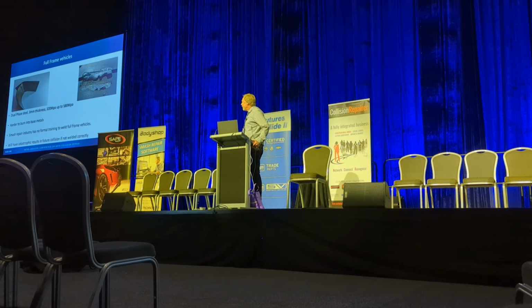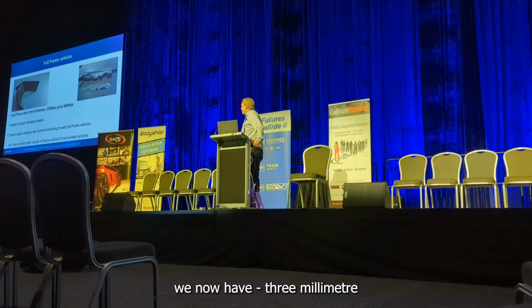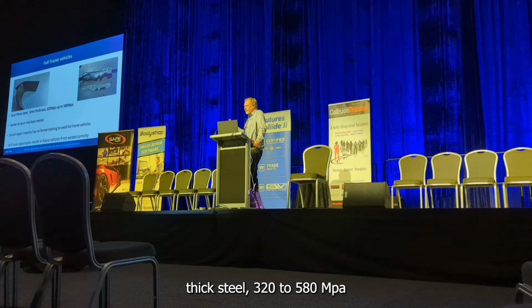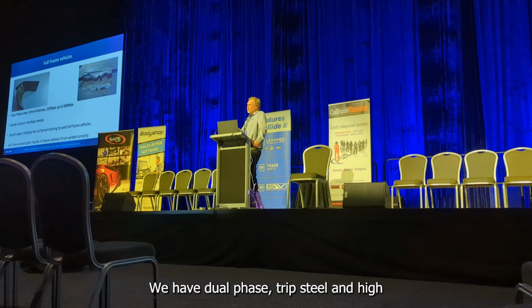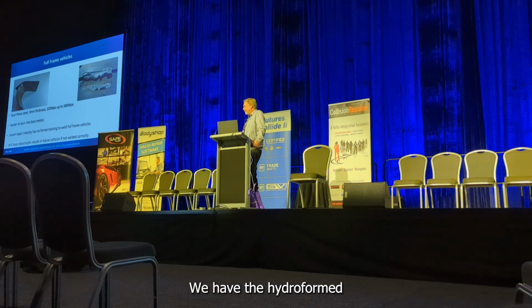So with these full frame vehicles, we now have 3mm thick steel, 320 to 580 MPa, but it doesn't stop there. We have dual phase, trip steel, and high strength steel. We have the hydroformed 700 to 800 MPa chassis. We can't weld them the same as what we weld mild steel. The base metal is harder to weld into. The settings need to be much higher, and your travel direction has to be different.